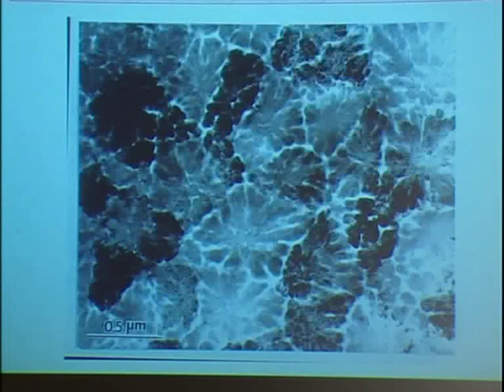This is what I saw. Each one of these, this is a single crystal. Looked like a dendrite. This is a single crystal. This is a single crystal. Also this and this and this. Look at these black ones. I have never seen such black crystals. When you see a black crystal in a bright field image, it means that the transmitted beam has very, very low intensity. That means that the diffracted beams have very high intensity because the energy goes somewhere.